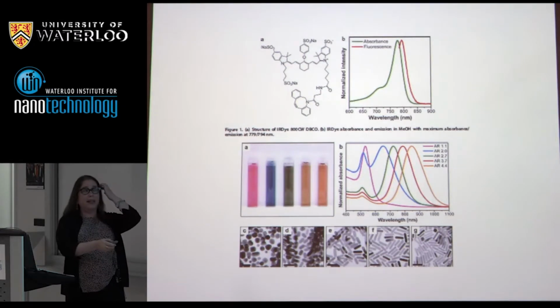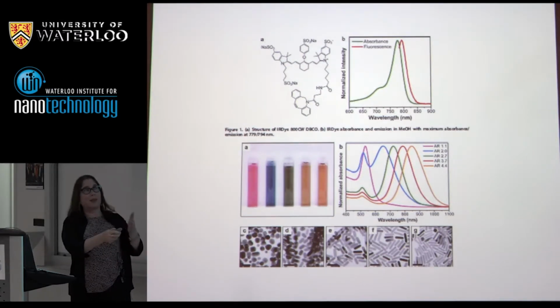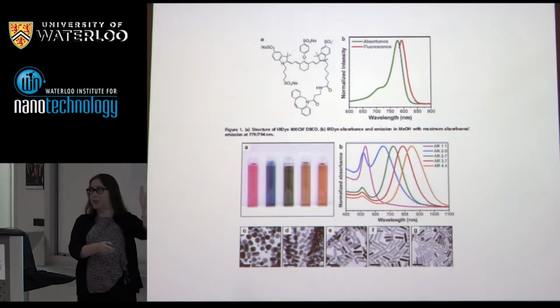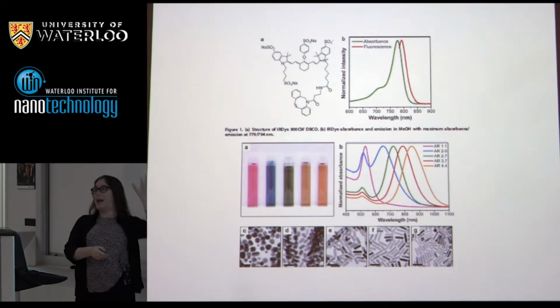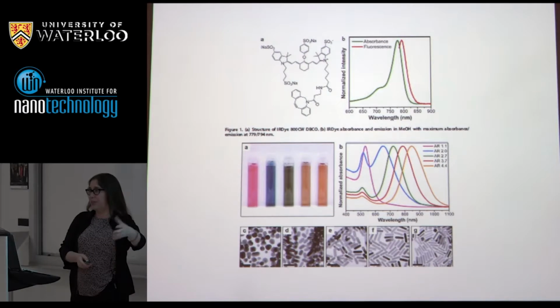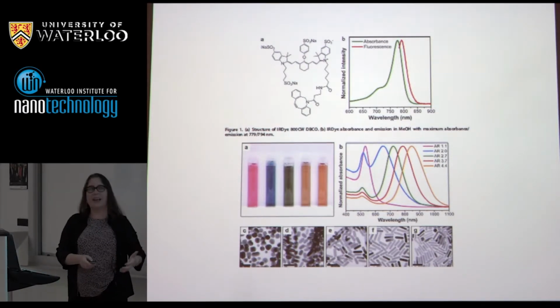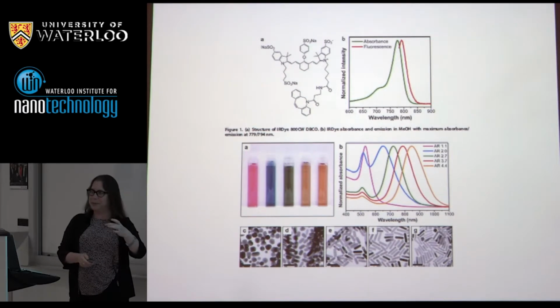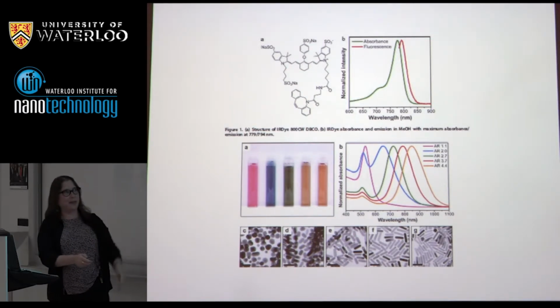What we're going to do is make a series of rods where our plasmons are going to be on the blue side, on top of it, on the red side of the absorption and emission here. The plasmon peaks are broad, so we're going to be on top of both absorption and emission, which is actually probably a good thing anyway for this. And then we're going to move the molecule further and further out by the silica spacer layer. Okay, so the particles, we know how to do that.